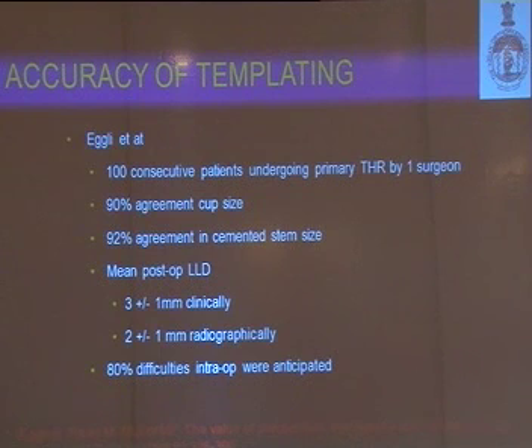So what's the accuracy of these templating procedures? Well, Eggli et al. studied 100 consecutive patients undergoing primary THR by one surgeon: 90% agreement in the cup size and 92% agreement in the cemented stem size. Of course, for the leg length discrepancy, it was within 1 millimeter clinically and about 2 millimeters radiologically. But almost 80% of the difficulties intraoperatively were anticipated with preoperative templating.